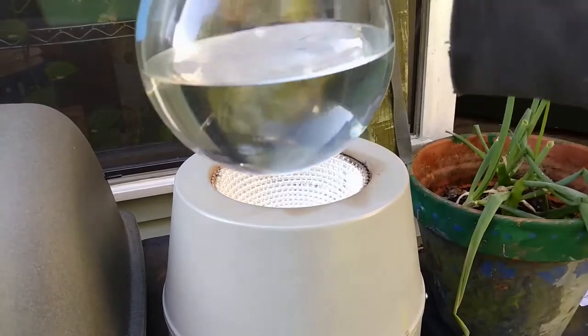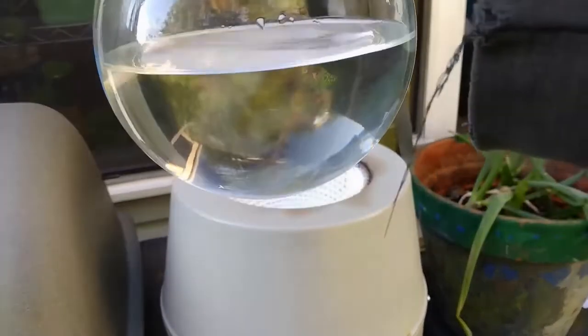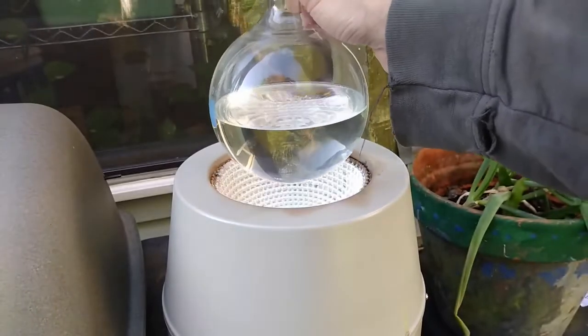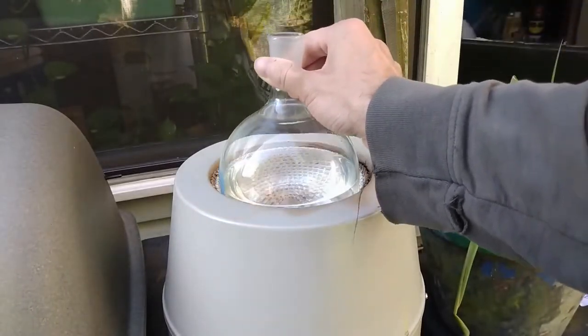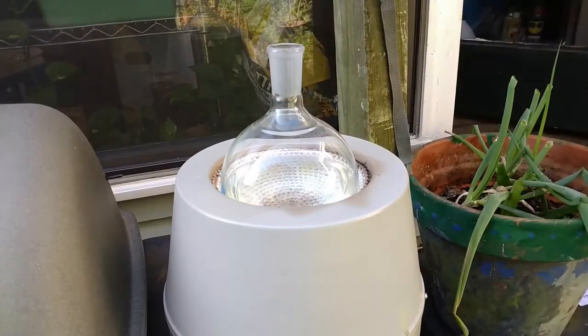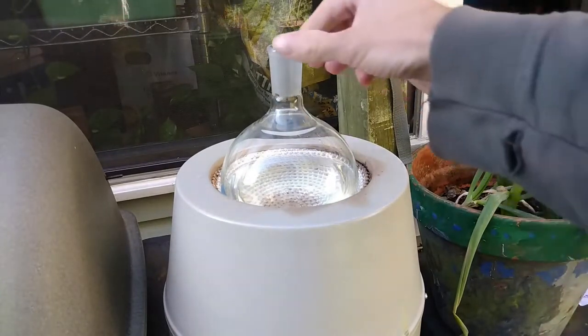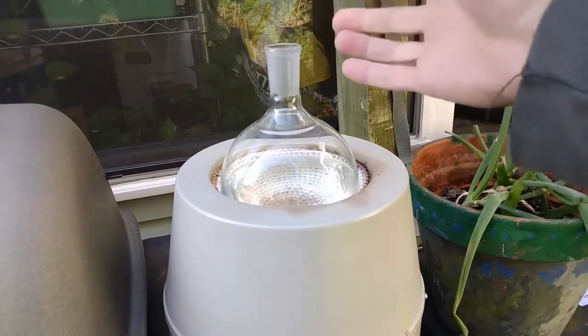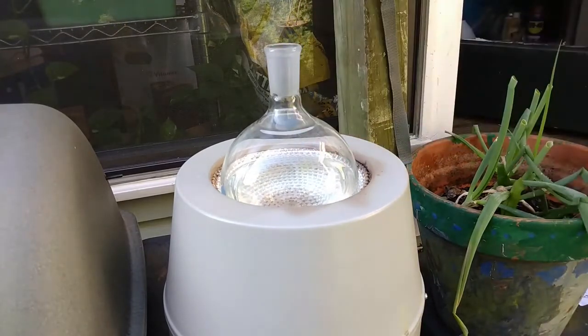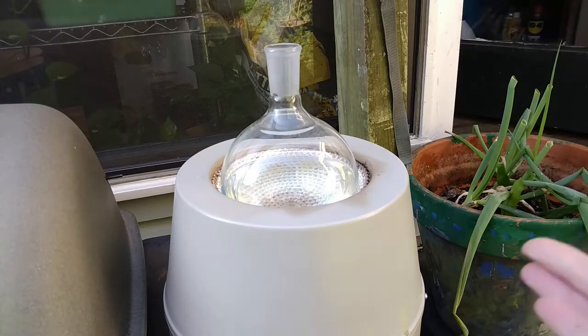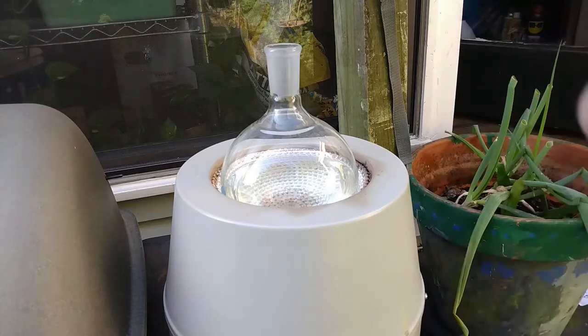Alright, so we are now ready to boil off the water in order to concentrate the acid. Definitely you should do this outside or under a fume hood. I don't have a fume hood, so I'm doing it here. At the beginning, it's mostly water that will boil off, but as the concentration of the acid will increase, the boiling temperature is going to increase too. And theoretically, we could reach a concentration of 98% at a temperature of 337 degrees Celsius.